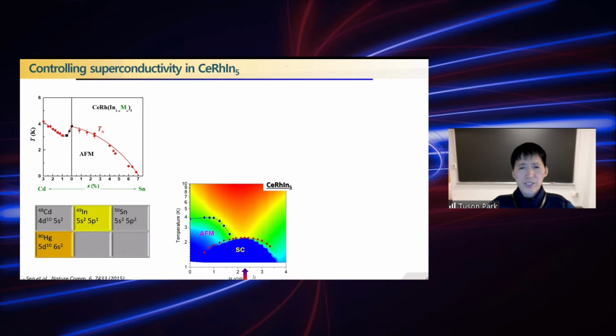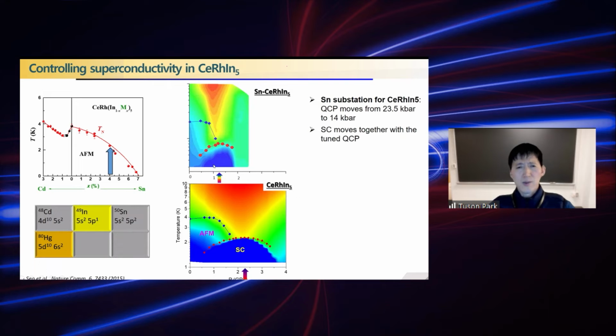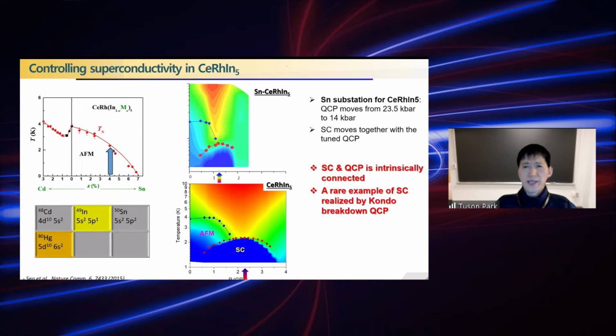So we show that the critical point is hidden inside the dome of superconductivity around 2.35 GPa, at the point where this strange metallic behavior occurs in the normal state. So what we did was that we did tin doping and then moved the T-Néel. What we found was that the critical point moves from 2.5 to 1.4. Not only did the AFM QCP move, but also the dome of superconductivity moved together with it, clearly showing that superconductivity and the critical point are intrinsically connected, which provides a rare example of superconductivity realized by this so-called Kondo breakdown.